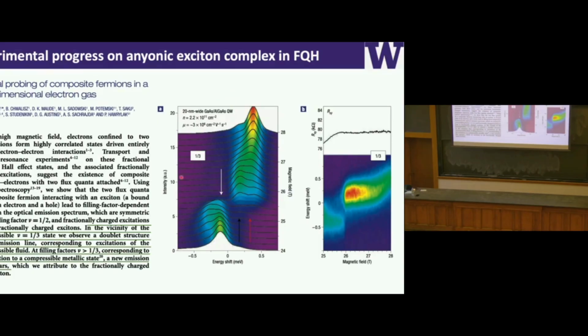And this is also emphasized by this middle plot, right? From top to bottom, what they do is tune the filling factor by magnetic field. And near the edge of the quantization plateaus, there's an emergence of new peaks at lower energies. So the paper, combined with theory calculations, claims that this new feature is a fractionally charged trion state, okay? The evidence basically is that when you dope this fractional state, you inject mobile anyons into the system, and they observe a new feature at lower energies. And this new feature is attributed to this fractionally charged excitonic state. Okay, so keep this feature in mind.